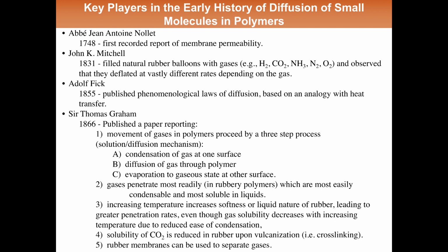He was studying the transport of salts through water. That was what had sparked Fick's interest in his work. But he was also studying the movement of gases through natural rubber membranes. And upon his studies, he postulated the basic mechanism by which gases transport through polymers, and he said that it occurs via condensation of the gas at one surface, diffusion of the gas through the polymer, and evaporation to a gaseous state on the other side.